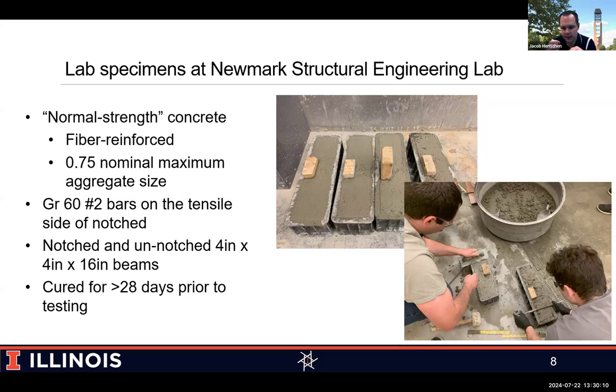The beams we cast to test are 4-inch by 4-inch by 16 inches, so they are not quite the standard modulus of rupture beams. We wanted something smaller, so that when we add these anchoring systems, we would hopefully see their effects more readily if we don't have such large specimens. And then just standard curing for 28 days to get to that 4,000 psi mark.